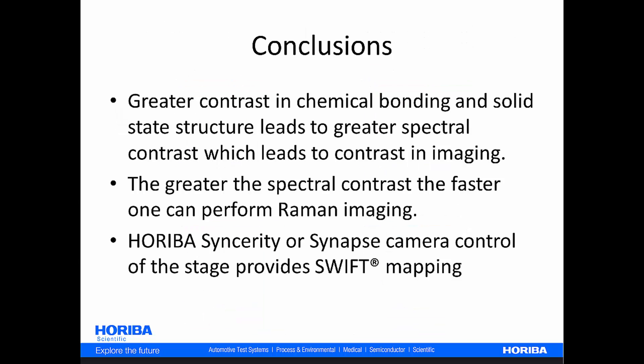So let me conclude then by saying that, again, in understanding Raman imaging and fast Raman imaging, the important consideration is that the greater the contrast in chemical bonding and solid state structure will lead to greater spectral contrast, which, of course, leads to better contrast in the imaging.